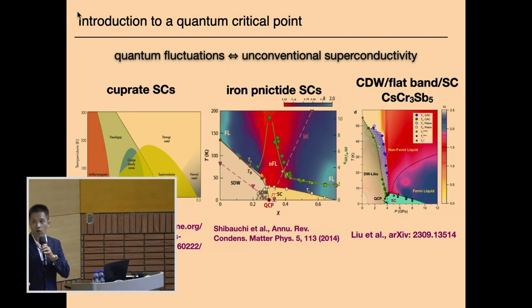Besides the fact they all look colorful, these three superconductors, cuprate superconductors, iron pnictide superconductors, and recently very hot charge density wave with flat band superconductor, cesium chromium 3 antimony 5, share signatures. Without tuning, the parent compound is not superconducting. This is the first signature they have shared. And the second signature is when a superconducting dome shows up,